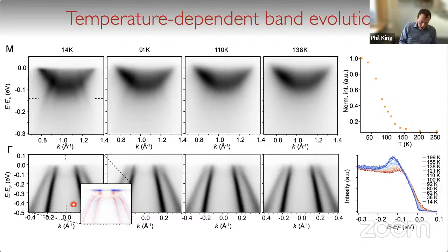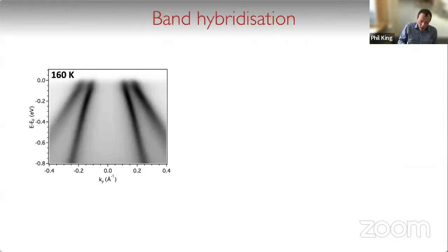And actually, if you look in these second derivative measurements, you can see that these backfolded conduction and valence bands appear to perhaps hybridize below the charge density wave transition, as you would expect them to do. And you can see this more clearly if we look at these high resolution measurements.